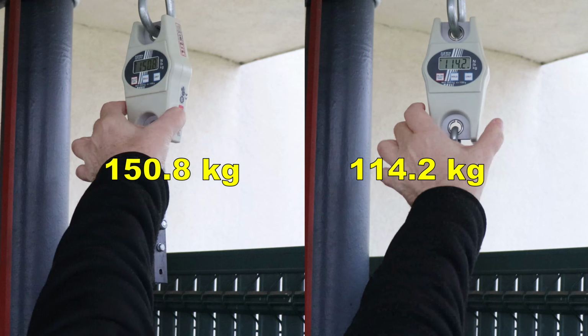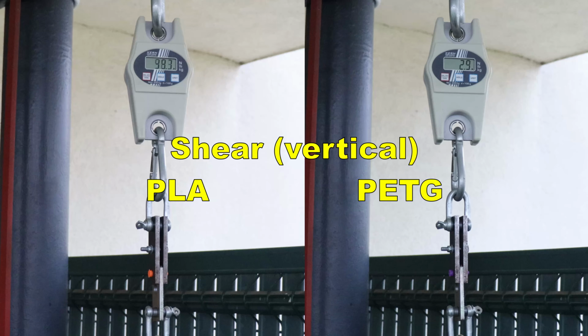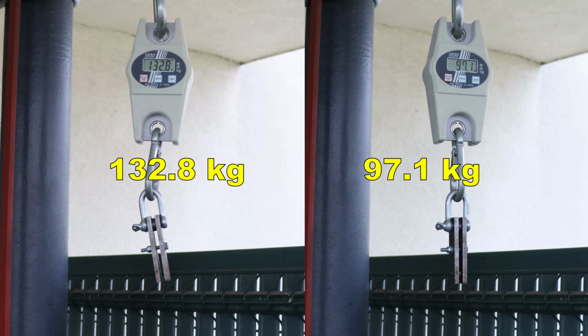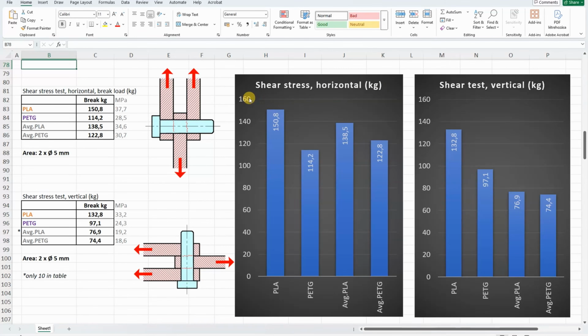Shear test, horizontal objects, side by side two materials. Vertically printed objects. Printed in horizontal position, PLA is stronger compared to the PETG, but this rate is typical for the average PLA and PETG materials. Now, printed in vertical position, the layer adhesion is very important, and thanks to this the PLA is extremely strong here, stronger than PETG, but this PETG is stronger compared to the average PLA and PETG together. Only pay attention that I have only a few test objects here, because I started this testing type much later.